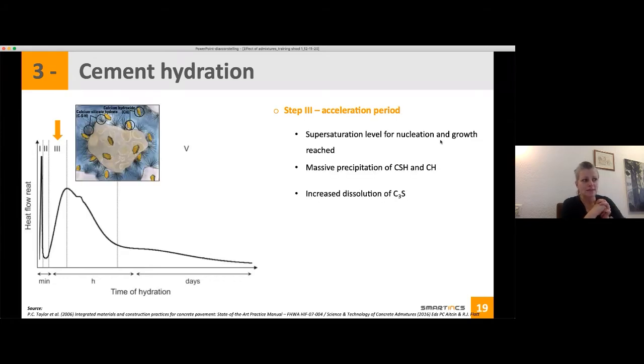And this is when you go to step 3. So step 3, as you can see, you have a very steep increase in heat flow. And that means you have a lot of nucleation, and it will grow. And at that time, you have massive precipitation of your CSH, so the hydration product from your silicate, and also your portlandite. And because you form a lot of products, it triggers more dissolution from your C3S to form even more. So it's also when you see the setting and the hardening of your cement paste. So at the beginning, when it starts to speed up, it's the initial set. And when it reaches an equilibrium is your final set.